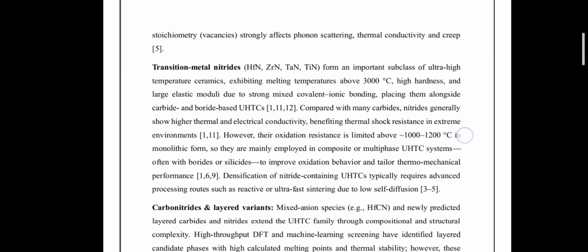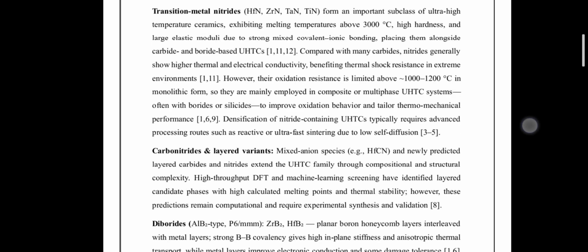Second one is the transition metal nitrides. The transition metal nitrides form an important ultra high temperature ceramic subclass with melting temperatures above 3000 degrees Celsius, high elastic moduli, and mixed covalent and ionic bonding. Compared with the carbides, nitrides generally show higher thermal and electrical conductivity and improved thermal shock resistance. Their key limitation is poor oxidation resistance above 1000 to 1200 degrees Celsius, so they are typically used in composites or multi-phase ultra high temperature ceramics. Densification of nitride containing ultra high temperature ceramics requires advanced processing methods due to the extremely low self-diffusion.